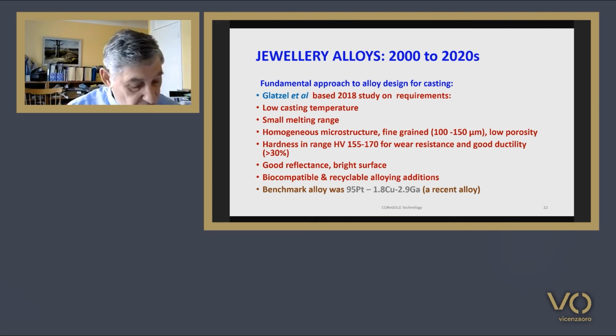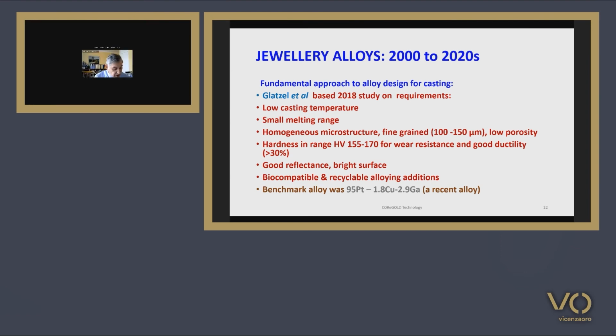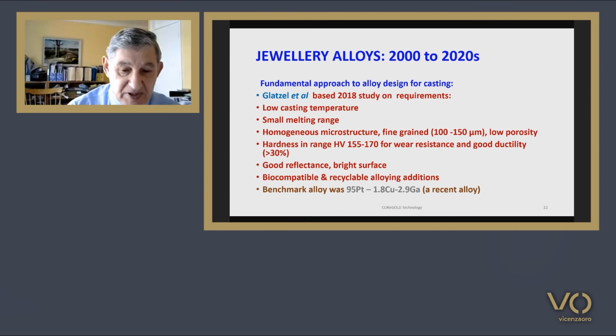porosity. Hardness in the range of 155 to 170 Vickers for wear resistance and good ductility in excess of 30%. They also wanted good reflectance and a bright surface, and the use of alloying elements that are biocompatible and recyclable. In their study, their benchmark alloy was a 95% platinum, 1.8% copper, 2.9% gallium, which is a recent alloy development.